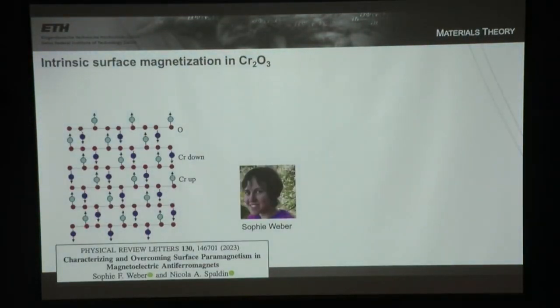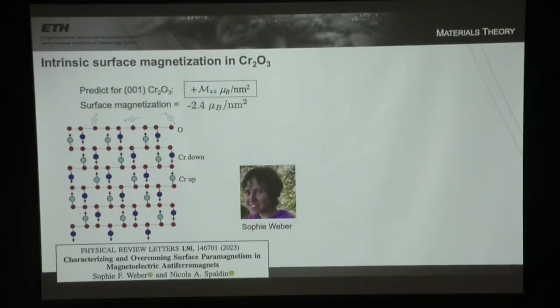So that one can assert, and Sophie Weber, who I think many of you know because she was a PhD student in the group of Jeff, actually came to my group and calculated this, and we started off with the stable 001 surface of Cr2O3. Sophie showed with spin dynamics that we had to cut off the top spins because they disorder at higher temperature than the bulk. And then she calculated the MZZ associated with this surface. She got a number. This was a number from density functional theory from a calculation.